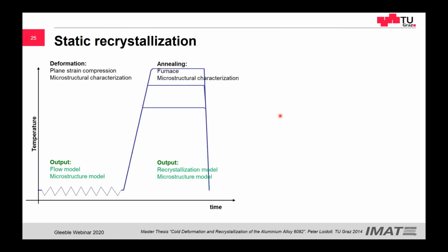Okay, what happens after cold deformation? We use this cold deformation, this stored energy, these dislocations, now to produce further structures during further heat treatments. And so what happens again, my very easy lines, the temperature-time. So we have our cold deformation. This is not really a change in the temperature, this is just to show deformation. And then we go up, we anneal and see what happens.